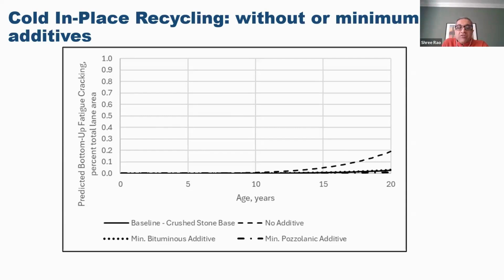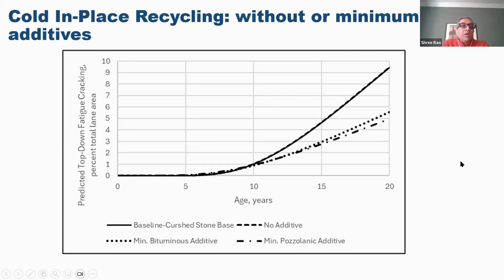The bottom up fatigue cracking, again, if you have no additive, there's quite a bit more bottom up fatigue cracking. But if you have some amount of additive in the cold in place recycling, in this case, the bottom up fatigue cracking was pretty low. Top down fatigue cracking, the baseline crushed stone base and the no additive had more top down fatigue cracking, and with the bituminous additive, the amount of fatigue cracking is reduced by about half in this case.